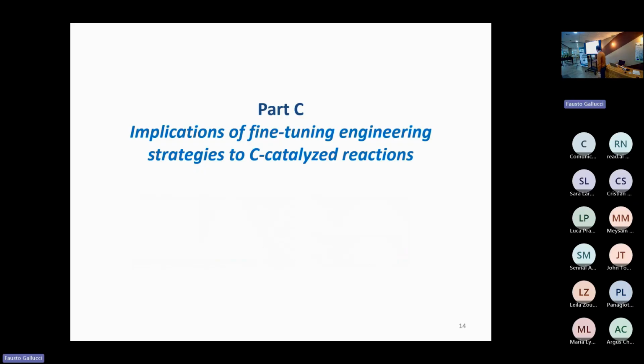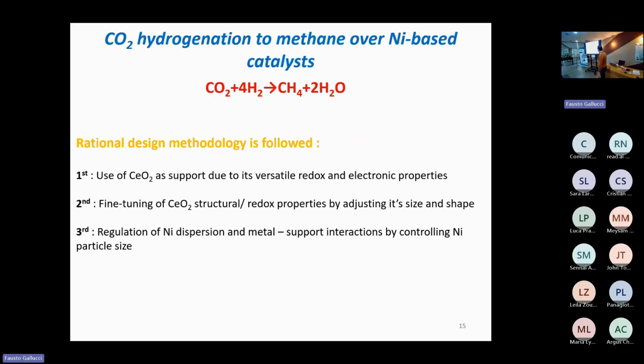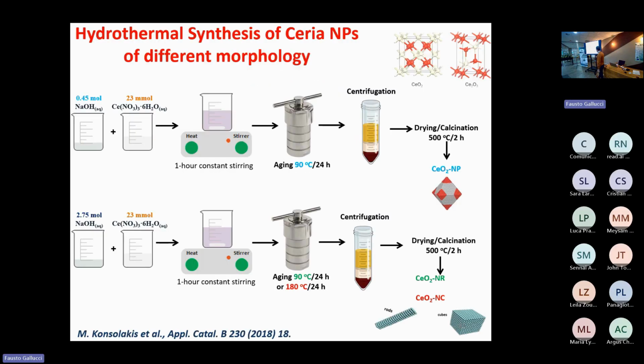Let's now proceed to the implications of these fine-tuning engineering strategies, starting from the Sabatier reaction over nickel-based catalysts. In this case, the rational design methodology that is followed involves at first cerium oxide as supporting material, due to its well-known versatile redox and electronic properties. Then we try to fine-tune the cerium oxide structural and redox properties by regulating the size and shape. And lastly, we regulate the nickel dispersion and metal support interactions by controlling the nickel particle size.